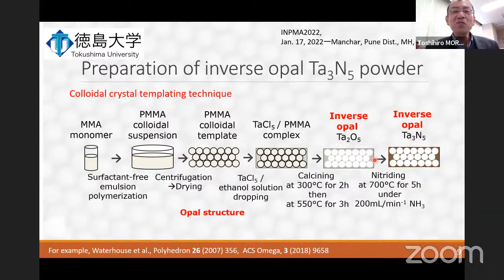to the preparation section. We used the colloidal crystal templating technique for the fabrication of the photonic crystal. Monodisperse PMMA colloidal spheres were first synthesized by the surfactant-free emulsion polymerization of MMA, methyl methacrylate. The PMMA colloidal suspension was centrifuged, and then the precipitate was collected by filtration. The filtrated PMMA spheres were dried overnight.